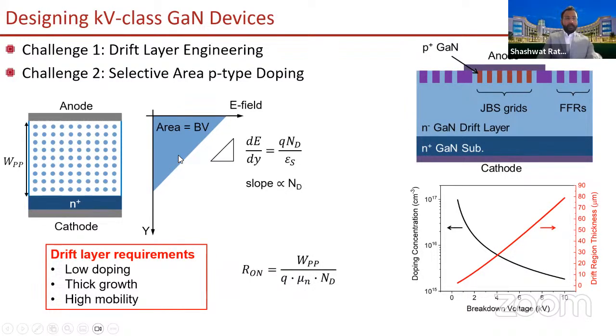The way this works is that when you apply an electric field to this material, the peak of the electric field would be at the surface, and then it will reduce as you move towards the depth of the semiconductor. The way this varies with depth will depend on its doping. The lower the doping, the shallower the slope. The higher the doping, the steeper the slope. The area of this triangle determines your breakdown voltage. You are integrating electric field over distance, and integration of electric field over distance gives you voltage.